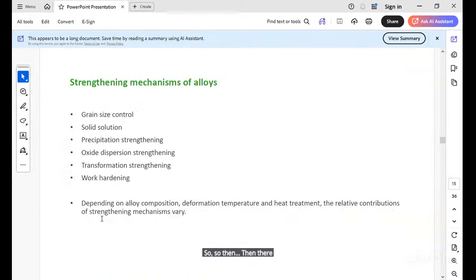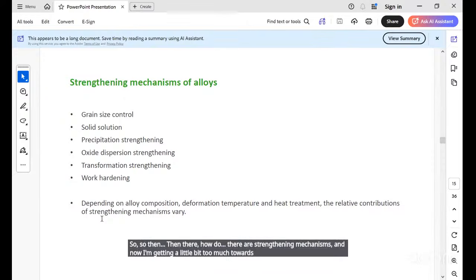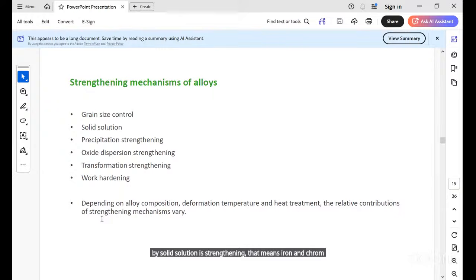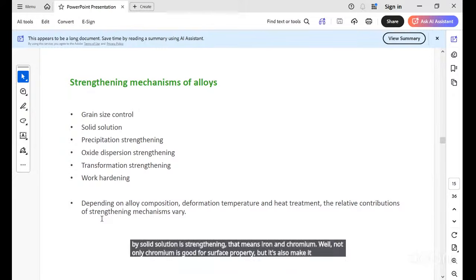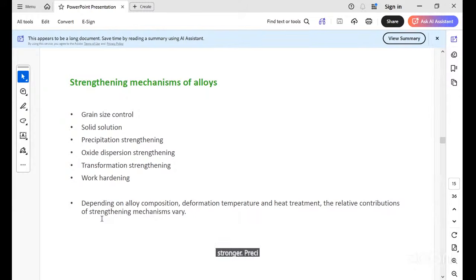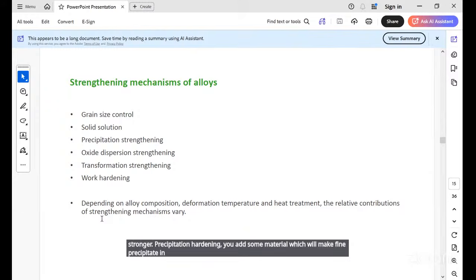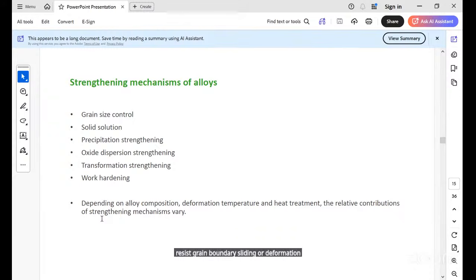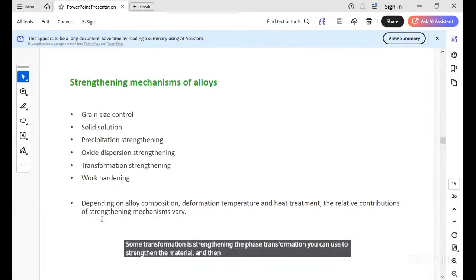Then there are strengthening mechanisms, and now I'm getting a little bit too much towards material science. There are ways to increase the strength of this material by grain size control, by solid solution strengthening. That means iron and chromium. Not only is chromium good for surface property, it also makes it stronger because it's slightly bigger than the iron atom, so it stretches the matrix, so it becomes stronger. Precipitation hardening: you add some material which will make fine precipitates in the structure of the alloy, which will help resist grain boundary sliding or deformation at high temperature. Transformation strengthening is where you use phase transformation to strengthen the material, and then just by deformation, the material becomes stronger. So there are different strengthening mechanisms.